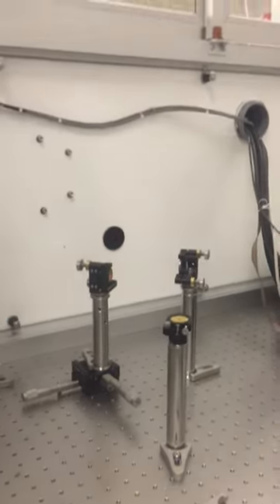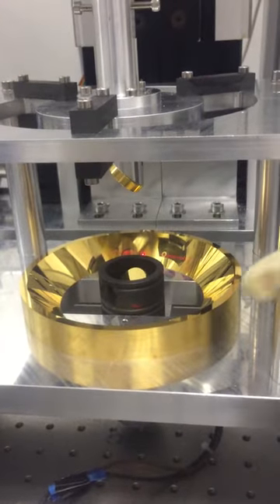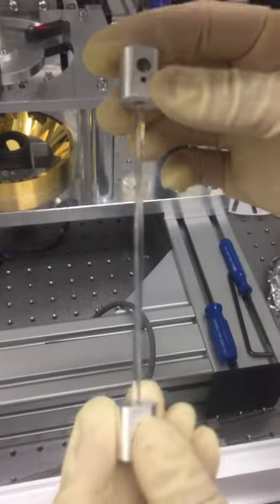What we have here is our fused silica fiber pulling machine. This machine physically makes the fused silica fibers that we use to suspend our optics. We have our laser beam coming in — it will hit this mirror in the middle, which is at 45 degrees. This actually rotates quite fast, about 80 times a second. That spins the beam out to this conical mirror, also at 45 degrees, which shoots it up to form a cylindrical beam. The cylindrical beam then hits off this conical mirror towards the stock. This stock in the middle is made of fused silica, and this is what we use to make our fibers. The laser heats it up in the middle, at which point the top stage of the pull machine then pulls this apart to create a fiber.